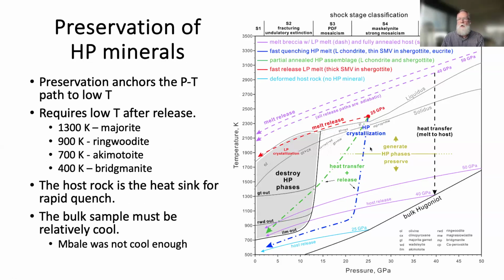The next thing is, in order to preserve the high pressure minerals, I have to end out below this gray field. This is the field where the high pressure minerals are destroyed. Garnet is the most robust, then ringwoodite, then ilmenite, and then Bridgmanite is way down below. Whatever my path is, it has to bring me down here in the end, right? And that is why we think that these are concave upward. And basically what is happening is, let me see. So we have to get down here.